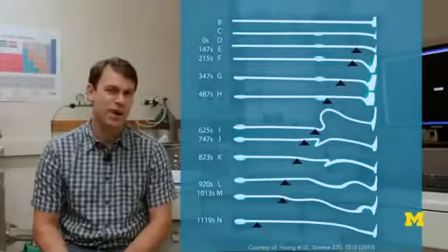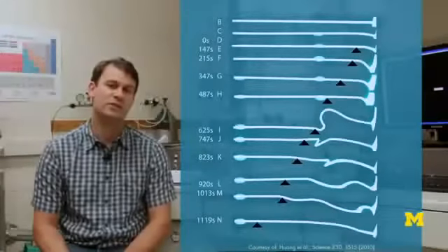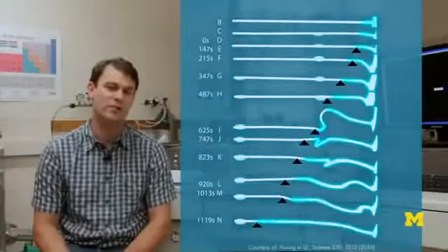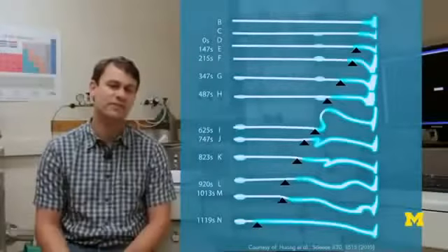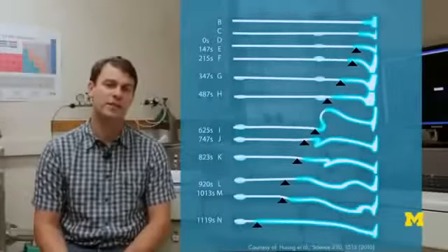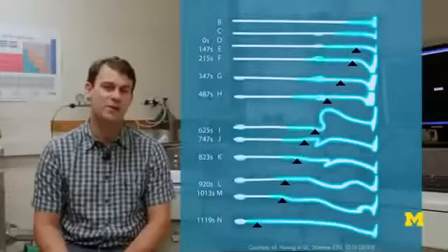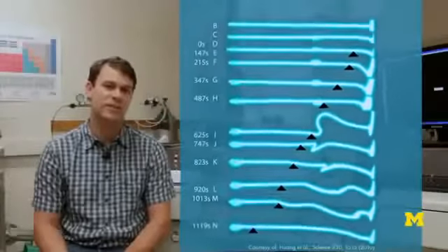So you'll notice there's a small triangle, and that indicates the location of the reaction front. So to the right of that triangle, we have the amorphous lithiated phase, and to the left, there's the crystalline tin oxide phase. So as time goes on, that reaction front moves from right to left, and you can see that the wire starts to kink up, it starts to bend. So in addition to that widening we talked about, the lengthening of the wire is also a manifestation of this increase in volume. So in this case, when we factor in the widening and the lengthening of the wire, there's about a 250% increase in volume of this system.